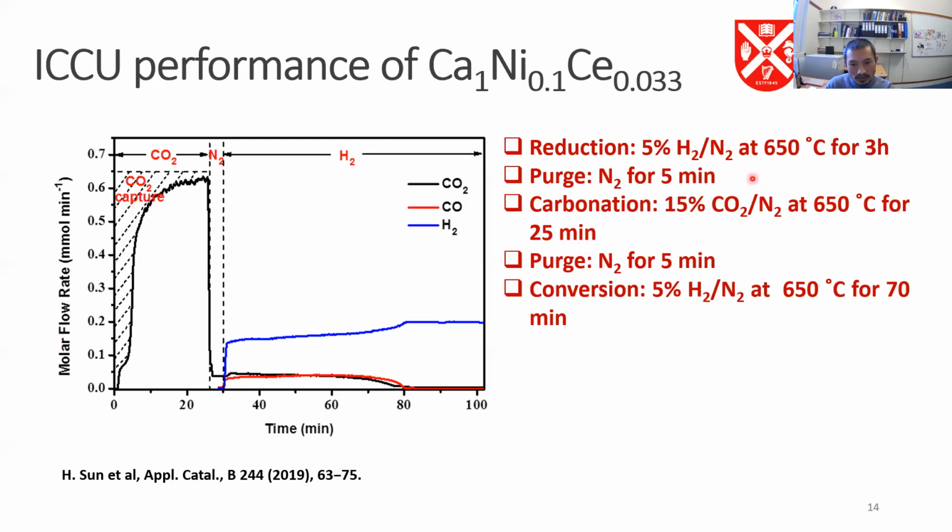Remember, here we didn't change the temperature. So here the CO2 adsorption is at 650, purge with nitrogen for 5 minutes, and then we introduce hydrogen at the same temperature, 650. Here the reaction time is quite long, 70 minutes. But you can also clearly see that the CO formation completes here. Okay? So that means most of the captured CO2 has actually been converted.